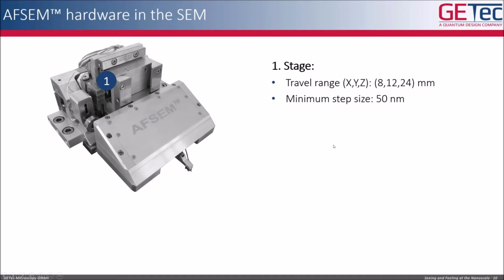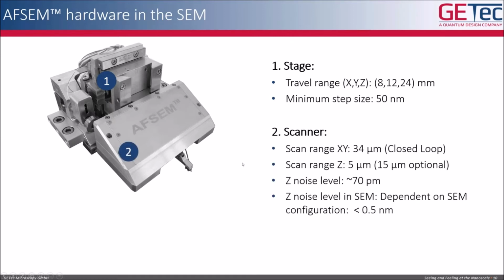a minimum step size in each of the three directions of around 50 nanometers. Then, of course, the heart of the system is the scanner itself. It's an XY closed loop scanner with a scan range of 34 micrometers in X and Y, and the scan range in Z is around 5 micrometers.